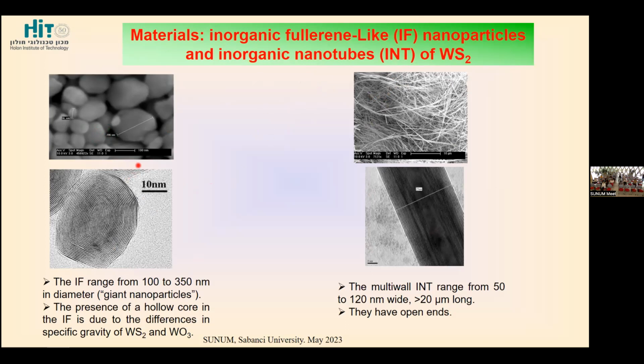properties. In the case of fullerene-like nanoparticles, these are multi-layer structures. They are sometimes called giant nanoparticles because their sizes range from 100 to 350 nanometers, and there is a hollow core and a lot of layers which we try to use for implantation of different species.